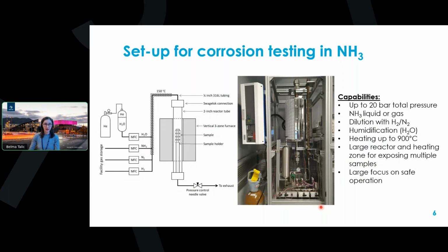To study the nitridation resistance of these alloys, we have at SINTEF established a dedicated ammonia corrosion rig that allows us to carry out exposures to ammonia containing gas mixtures at up to 20 bars of total pressure and temperatures up to 900 degrees centigrade. And the rig itself consists of an alloy-based reactor with Swagelok components, as you can see pictured inside the furnace here. And we have a needle valve at the outlet, pictured here, where we have pressure control.